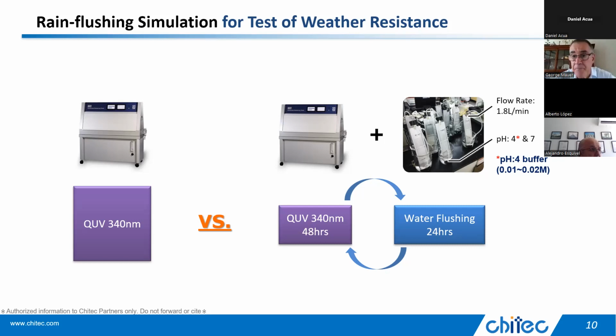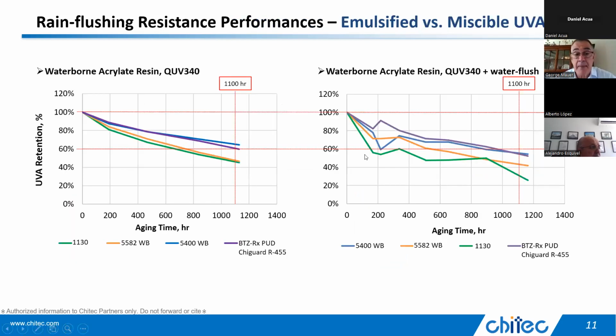So we did, you can see a little test up here, a setup where we simulate rain. So we just run water across the coating. We did pH 4 and 7, and the reason we did 2 pHs is just to simulate acid rain at pH 4, and then we did neutral rain for places that don't get acidic rain to see if there's a difference. Turns out there wasn't a difference, which surprised me, but okay. But what we did see was that when you introduce the water test, the 1130 is weaker.